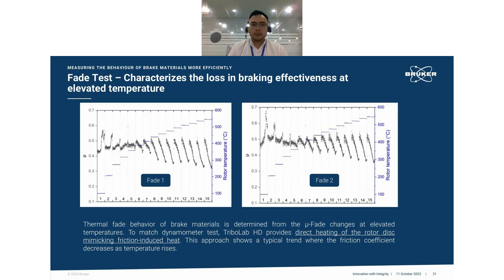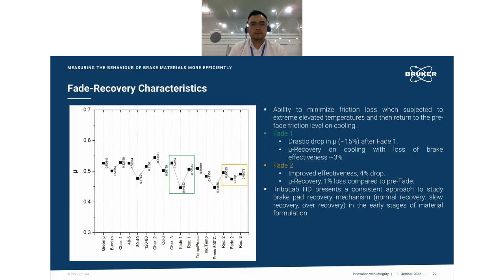materials from the coefficient of friction in both fade one and fade two, how they change at elevated temperature. So to match the dynamometer test, the TriboLab HD provides direct heating of the rotor disc, so as to mimic a friction-induced heat scenario. Our sample is small, so we need to supply it with external heat such that we can bring the rotor disc temperature up to the elevated temperature that's required in the fade testing. A general approach that we expected in the results is a typical trend where the coefficient of friction decreases as temperature rises. But moving from fade one to fade two, there is some recovery where the coefficient of friction slightly increased, showing that the brake pad actually recovers after a few of the recovery steps, which is shown in this chart or plot, which shows the fade recovery characteristics.